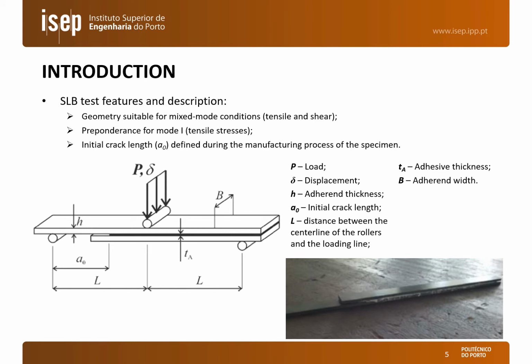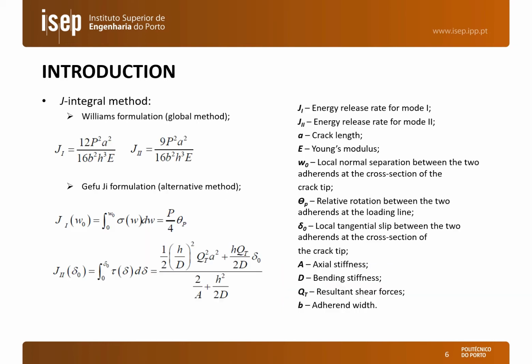In this figure we can see the single leg bending test geometry, which is suitable for mixed mode conditions, although it has a higher preponderance for mode 1, and it has an initial crack length a0, which is defined during the manufacturing process of the specimen. In this figure we can see all the geometric variables that are relevant to the specimen, and we can see that this is also a 3-point bending test in which one of the adherends is shorter than the other, thus creating a mixed mode loading.